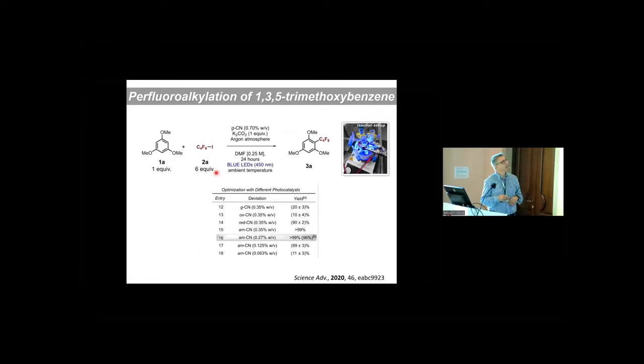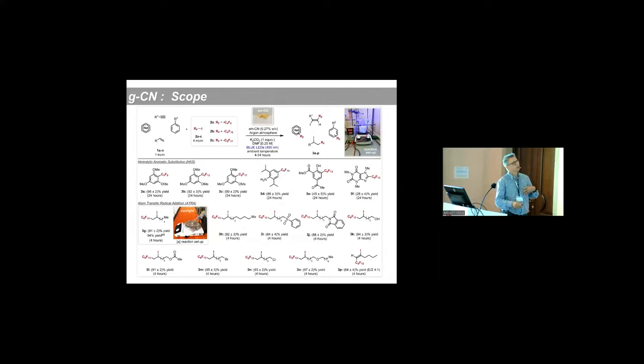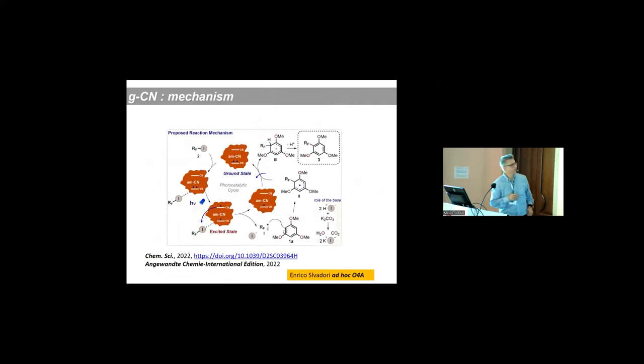Here is a first example. Depending on the treatment we apply on this standard material, like amorphization, reduction, oxidation, and formation of different functionality on the surface, you can see that the yields in this specific reaction go from 10 to 99 percent. So the surface of this material is extremely important, and then you can see how many different reactions you can perform. These are important materials for liquid crystal preparations, for agricultural products, for pharmaceutical products, and so on and so forth. The reaction mechanism is still under investigation.